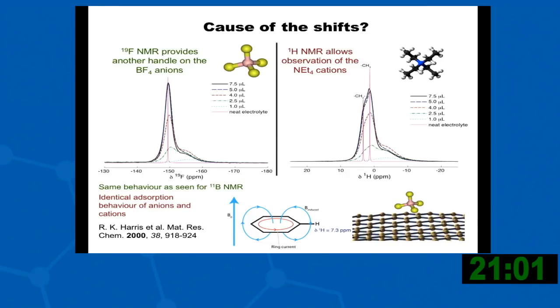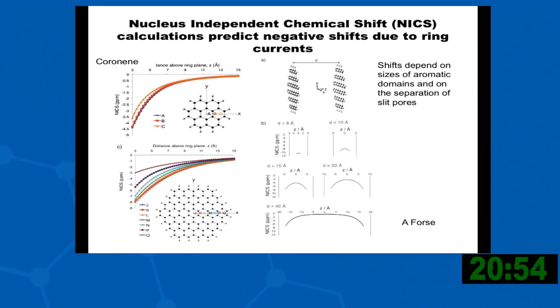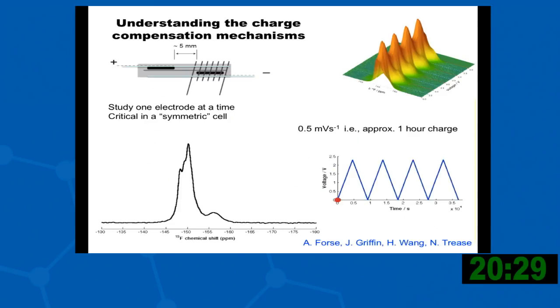And what's interesting, if you look at the fluorine NMR, you get the same shift. If you look at the proton NMR and the boron NMR, it's all the same. And so we can calculate this via so-called nucleus-independent chemical shift calculations. And what we do is we take an anion and we move it closer to increasingly large fragments of carbons, from coronenes to circumcoronenes to dicircumcoronenes. And as we move closer to the surface, we get a bigger shift that depends on the size of the graphene fragment. So we understand where these shifts come from.